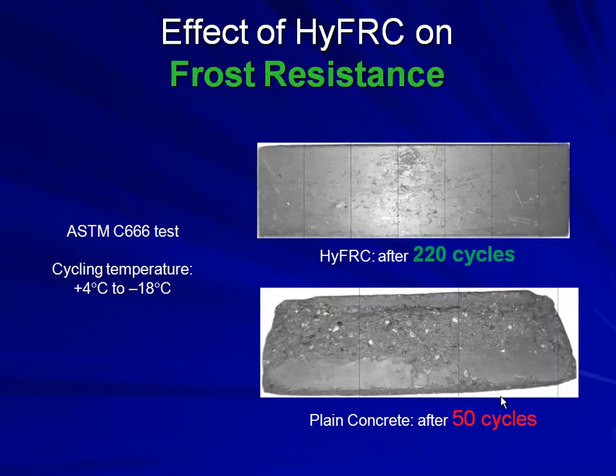Frost resistance, this is, I think, very clear. This is your hybrid fiber reinforced after 220 cycles. We followed the ASTM standard in this case. This is your conventional concrete. There are many, many other tests we performed, but due to time constraints, I will not go into that.